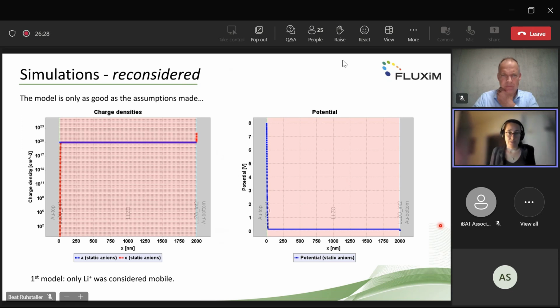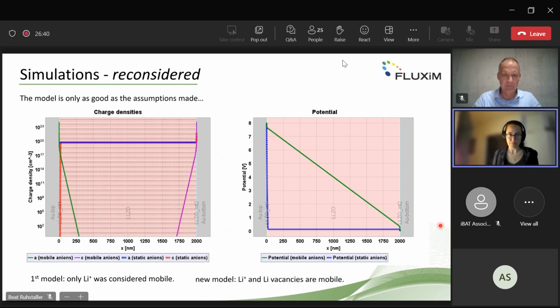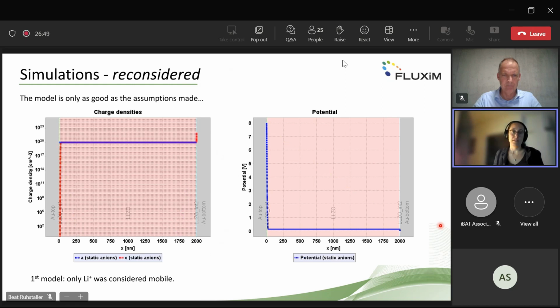So the model is only as good as the assumptions made there. And in the first model approach, we simply assumed that we only have one mobile species, namely the lithium plus ion, or the cation. And as you can see already before, there was a strong accumulation here, but most of the device had no change in the concentration. And this is because we also have the static anions, which compensate or fix the cations, and so there was no change, and there was in the end kind of a flat potential or even no potential.